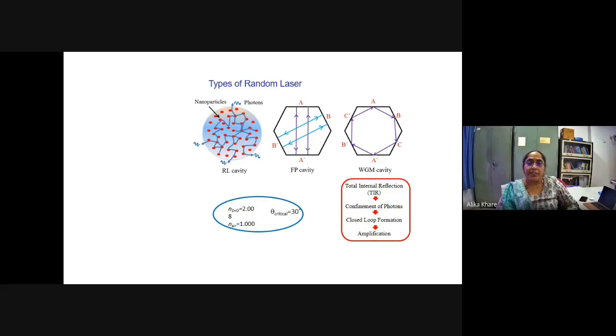If the angle of incidence happens to be more than the critical angle - for ZnO the refractive index is of the order of 2, and outside is air, which has 1 - if we calculate from Snell's law, the critical angle comes out to be 30 degrees. So if the angle of incidence happens to be more than 30 degrees, the complete radiation will undergo internal reflection.